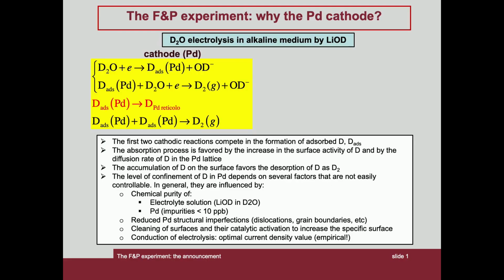The Fleischmann and Pons experiment. Why the palladium cathode? The first two cathodic reactions compete in the formation of adsorbed deuterium. The absorption process is favored by the increase in the surface activity of deuterium and by the diffusion rate of deuterium in the palladium lattice. The accumulation of deuterium on the surface favors the desorption of deuterium as a deuterium gas. The level of confinement of deuterium in palladium depends on several factors that are not easily controllable.